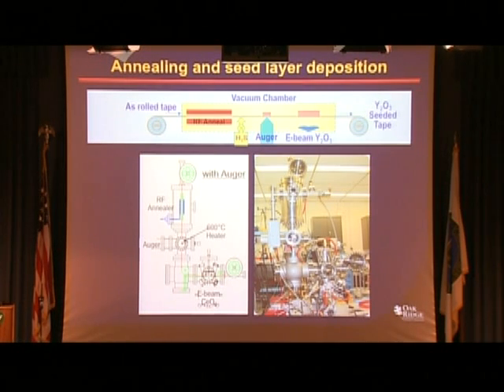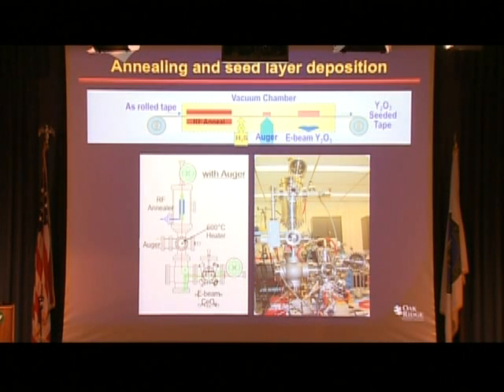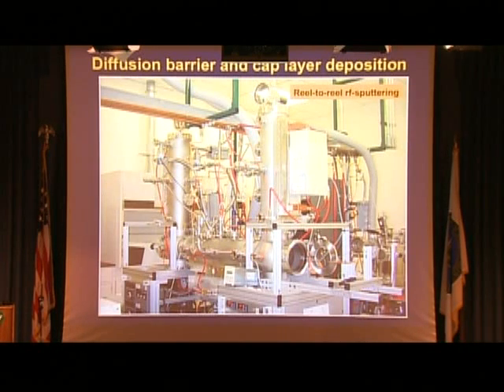This is a cartoon. This is what the actual system looks like. We anneal it in a high temperature to form the nice texture. We leak a small amount of H2S gas, which automatically forms this surface reconstruction on the tape. We measure it by Auger just to make sure everything is going OK, and we deposit the first layer with a process called electron beam evaporation. We then put this tape into another system that we designed at Oak Ridge, now of course transferred to American Superconductor, the process going from one reel to another with 3 linear sputtering guns, and we deposit 2 other layers called the diffusion barrier and the cap layer, and I'll get to that in just a second.